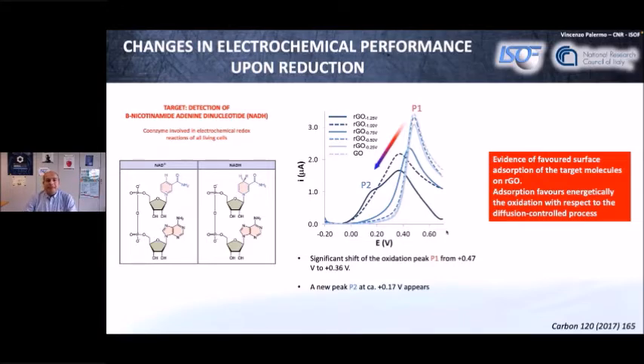Okay, so why does this happen? Of course, these are complex molecules that are interacting not with perfect graphene, but with a complex surface. But anyhow, the evidence we got, and you can see more details in this paper that we published in 2017, is that these kinds of molecules need a conductive substrate to adsorb on. But they also need some oxygen-containing chemical groups to favor this adsorption. And once they are already adsorbed on the surface, the overpotential needed to oxidize them is lower. So you can detect these molecules by applying a lower potential.